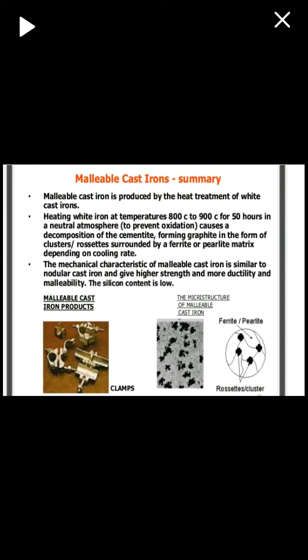Malleable cast iron summary. Malleable cast iron is produced by the heat treatment of white cast iron. Heating white iron at a temperature of 800 to 900 centigrade for 50 hours in a neutral atmosphere to prevent oxidation causes a decomposition of the cementite, forming graphite in the form of clusters or rosettes surrounded by a ferrite or pearlite matrix, depending on cooling rate. The mechanical characteristics of malleable cast iron are similar to nodular cast iron and give high strength and more ductility and malleability. The silicon content is low.